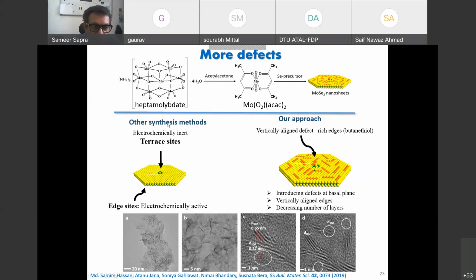If you look at most of the other methods, CVD or MBE or exfoliation, then what you get is very neat looking triangular, sometimes more hexagonal sheets. Very clean looking sheets. But when you look at the ones that we make, these are all crumpled sheets. You see this TEM image. And why they are crumpled is because all of this selenium precursor does not react completely, and there are a lot of defect sites that are created on the basal planes. The moment you have less selenium on the surface, the molybdenum atoms below it are kind of non-bonded and they try to attract the nearby seleniums, therefore folding the sheet. And that's how all these crumples occur in the sheet. These can be seen very clearly in the images. But I'll tell you that these defects are very useful for us in a moment.